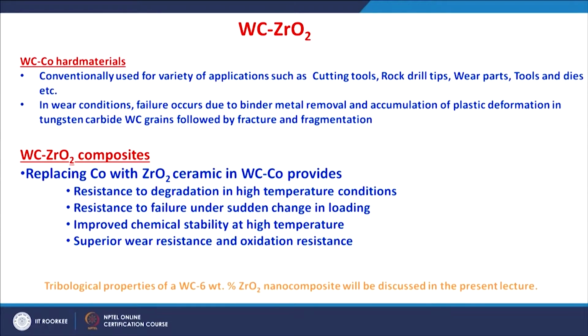In wear conditions, the failure of these tungsten carbide based materials, particularly the tungsten carbide cobalt hard material, occurs mainly due to binder material removal and then the fracture and fragmentation of the ceramic material. If we can replace this metal binder of cobalt with zirconia ceramic, we can have an improved resistance to degradation in high temperature conditions.